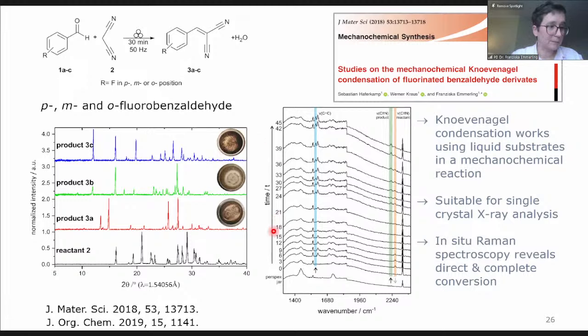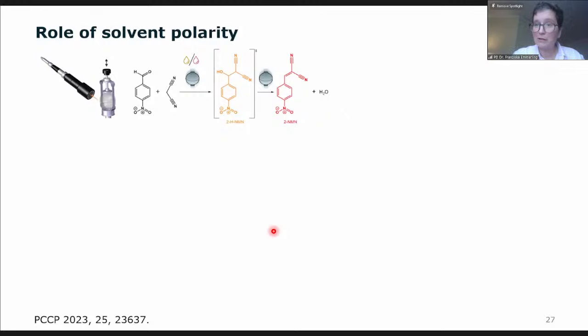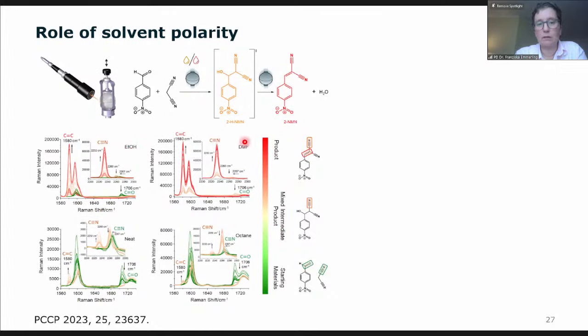And here in a recent study, we went back to the first example I showed you, using the nitrobenzaldehyde and malononitrile, and we were looking at liquid-assisted grinding reactions, and also were interested to know more about the influence of the solvents and the polarity of the solvents. Here you see the data for different solvents, ethanol, DMF, and also neat grinding, and as the non-polar solvent we use octane. If you use polar solvents, we have more or less a direct conversion to our final product. If we use neat grinding or the non-polar solvent, we get an intermediate. So you see here the green lines, we form the starting materials, and here in the intermediate phase, we have the hydroxyl compound.